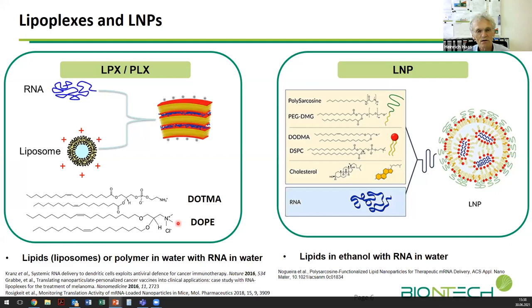Two typical lipids we use for lipoplexes are DOTMA, a cationic lipid, and DOPE, a helper lipid known to be favorable for endosomal uptake and processing. In contrast, LNPs are manufactured using a lipid solution in ethanol with a more complex lipid composition, comprising cholesterol, phospholipids such as DSPC — a fully saturated phospholipid in the gel phase at room temperature — and importantly, a stealthy moiety for particle engineering to arrive at optimized particle properties upon injection.